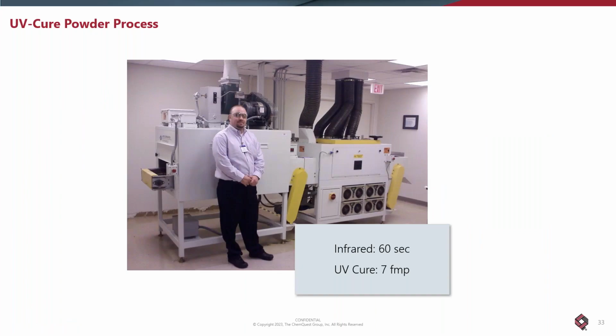Here's a picture of a UV cure pilot line I used to have in my lab. It's one of our lab technicians. Basically, this was a 60-second flat line infrared, followed by two banks of 600 watt per inch UV cure lamps, emitters. And we did this at, the cure was measured, 7 feet per minute and got complete cure of a nicely formulated UV curable product.